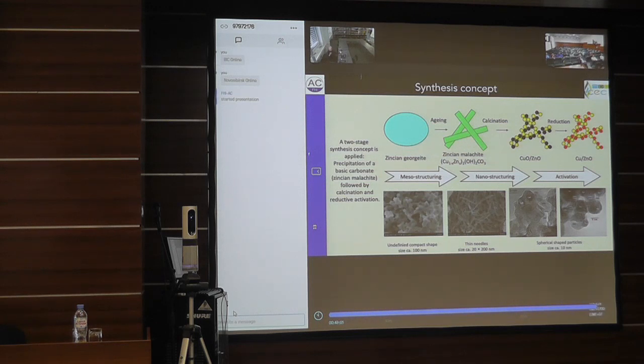But of course, by knowing what we do, we were able to optimize this, and the optimization makes the company with which we collaborate making a catalyst that is now about 2.5 times more active than it was 20 years ago. And that comes simply from optimizing these operation steps. The chemical composition is still the same as it was in the year 2000. But the way how you make it is not the same anymore.